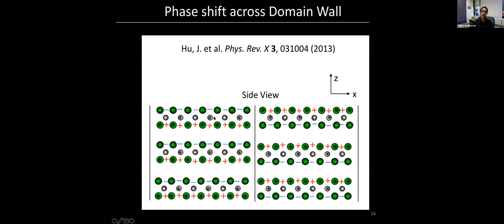But in any case, what you find is that the sign of the order parameter switches from the top to the bottom layer. So there's a pi phase shift in the sign of the order parameter between the top and the bottom selenium or arsenic layers. So this would be very hard to probe unless you looked at a monolayer.